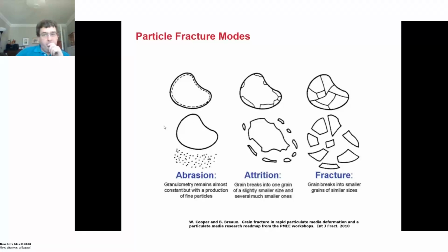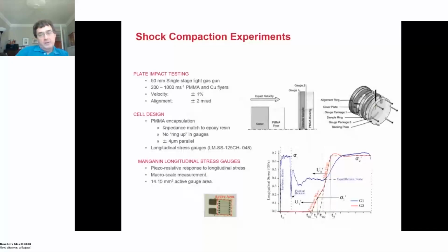When we did shock compaction experiments, our initial ones were looking predominantly at the global shock response, trying to determine the Hugoniot of the material. Here, we're doing some experiments. You'll notice instead of a copper container, we have a Perspex, a Lucite, a plexiglass container, and we are impacting at lower velocities, lower stresses in the system, and we're looking for better time resolution in the gauges.